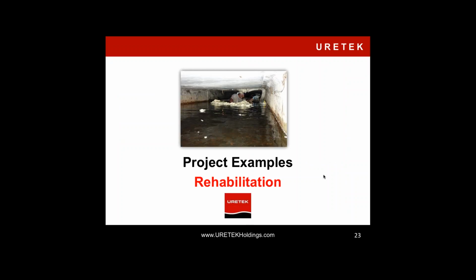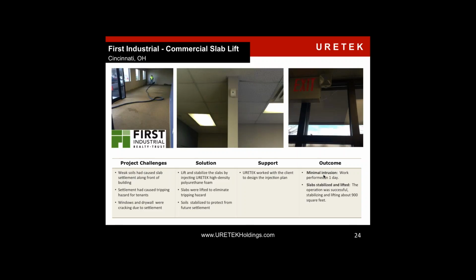Talk about rehabilitation. Here I had a project down in Cincinnati, a commercial slab lift. The slabs had wound up settling, causing deflection in the ceilings, as you can see above, cracking windows, binding doors, and creating trip hazards. So high-density polyurethane was injected underneath the slabs, expanding, with monitoring, and bringing those slabs back up to grade, eliminating the trip hazards and bringing the structures back into alignment. The nice thing is this was done all within a day with no disruption to the business. Again, holes are only about 5/8 of an inch, so they're able to work with the carpet, just cutting a small flap through, drilling, vacuuming, cleaning everything up, and all those holes are grouted closed and the carpet replaced.